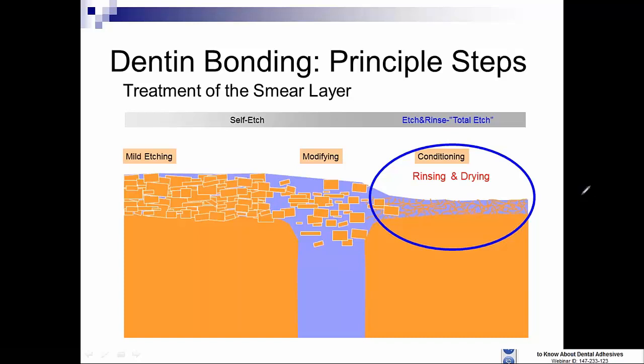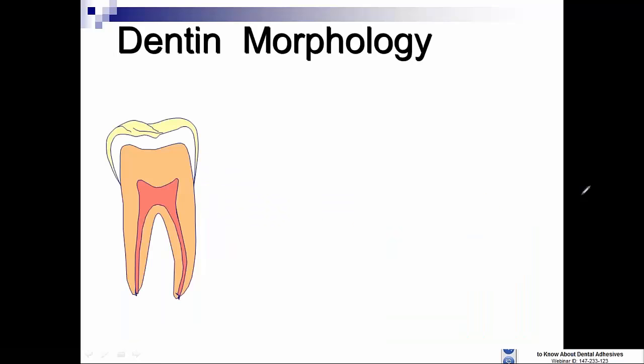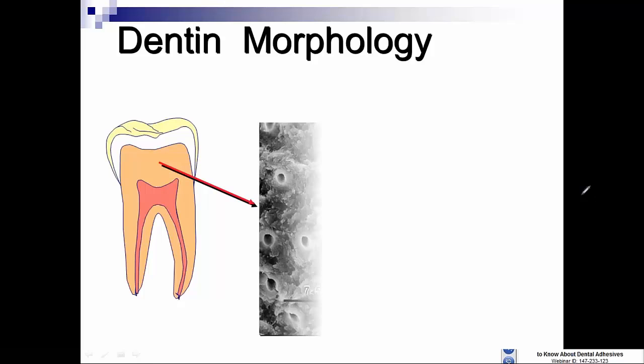If the collagen is overdried after phosphoric acid conditioning, it will present a barrier to the penetration of adhesive monomers. If you recall what I said about dentin bonding and bonding in general being removing mineral apatite and penetrating monomers into the holes that were made, if the collagen is dried, then underlying the dried collapsed collagen layer will be unpenetrated areas, air spaces, where the monomer has not penetrated, leaving a gap underneath the adhesive layer and ultimately underneath the restoration. Now, the propensity for this to happen depends on which part of the tooth we're dealing with.